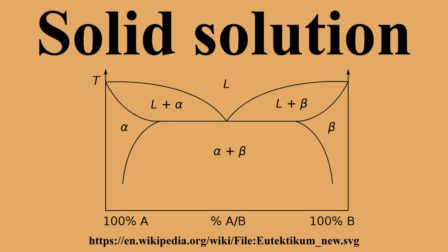Take the alkali feldspar minerals for example, whose end members are albite, NaAlSi3O8, and microcline, KAlSi3O8. At high temperatures Na+ and K+ readily substitute for each other, and so the minerals will form a solid solution. Yet at low temperatures albite can only substitute a small amount of K+, and the same applies for Na+ in the microcline. This leads to exsolution where they will separate into two separate phases. In the case of the alkali feldspar minerals, thin white albite layers will alternate between typically pink microcline